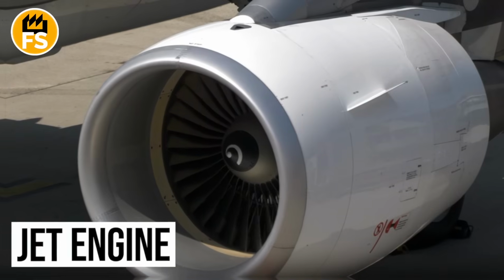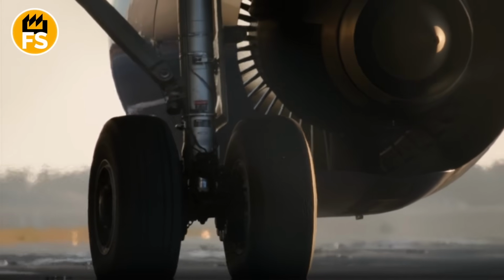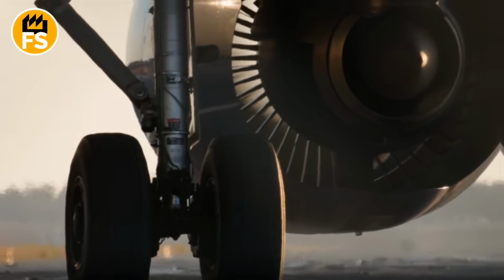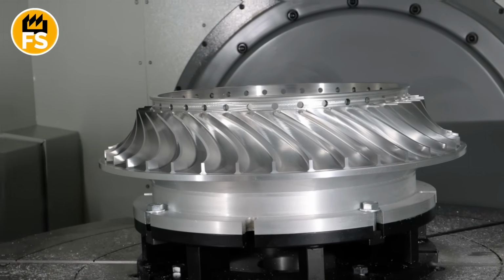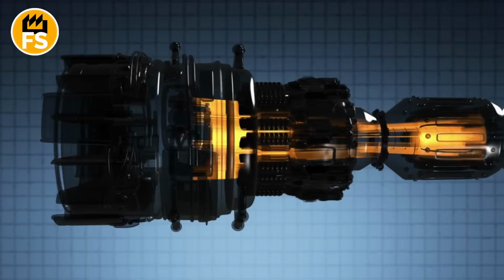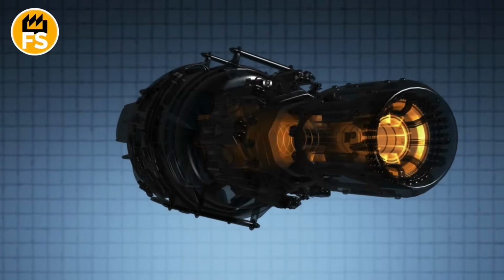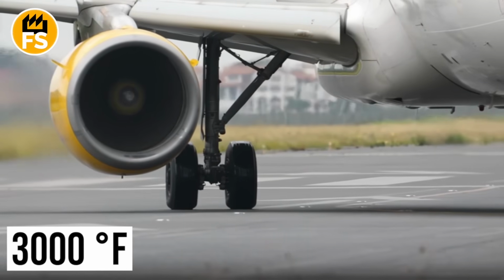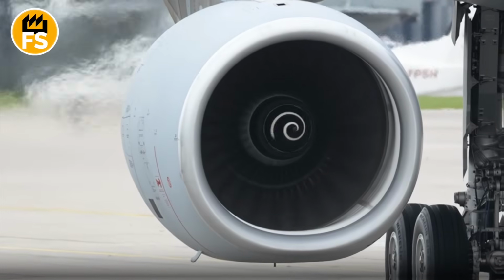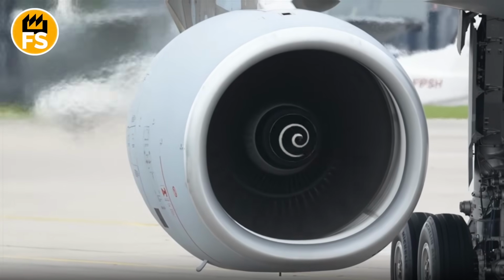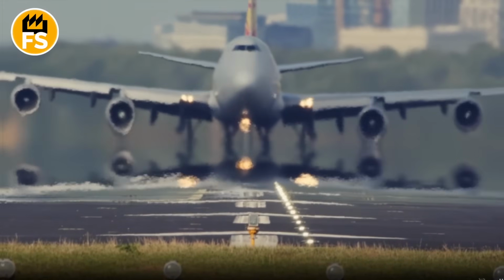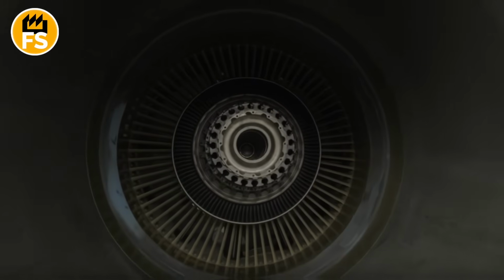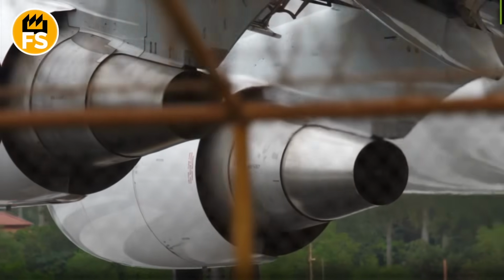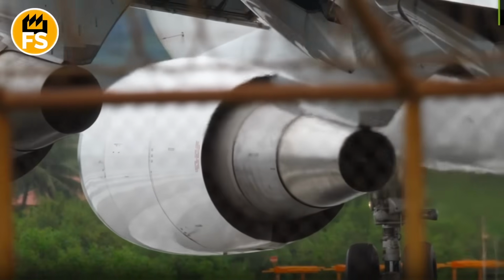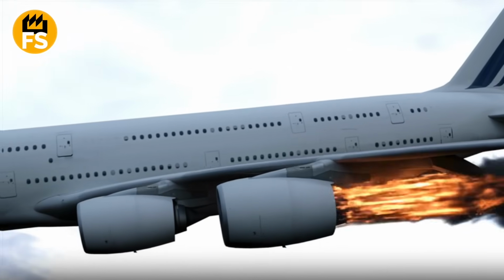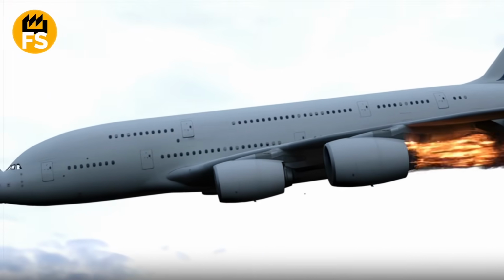The answer: jet engines. Close to 80% of all rhenium goes into the aviation industry to manufacture superalloys used for making turbine blades. A jet engine turbine blade operates in absolute hell. Gas temperatures hit 3,000 degrees. Pressure is massive. The blade spins at tens of thousands of revolutions per minute, experiencing loads of hundreds of tons per square inch. Corrosive environment with sulfur impurities from aviation fuel. And all of this for years of continuous operation with zero margin for error. If a blade cracks mid-flight, the engine disintegrates, the plane goes down.